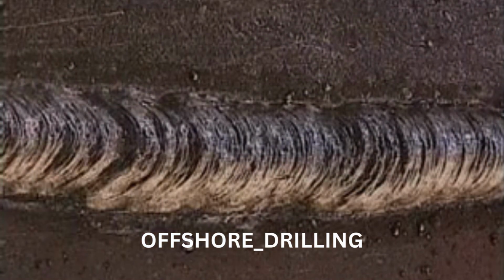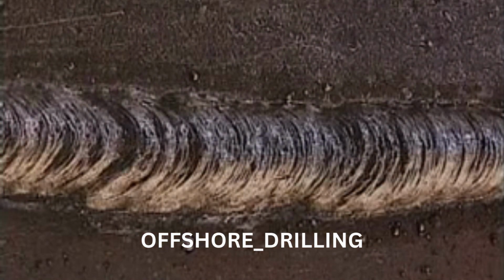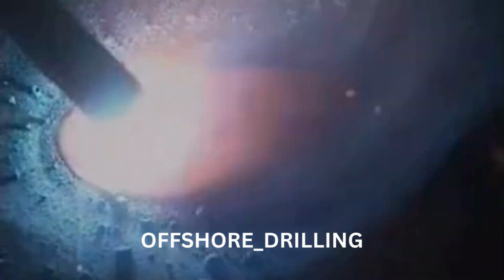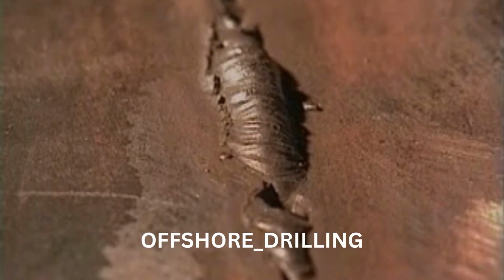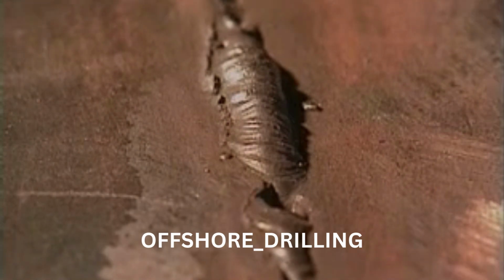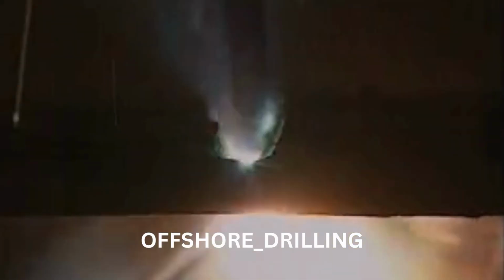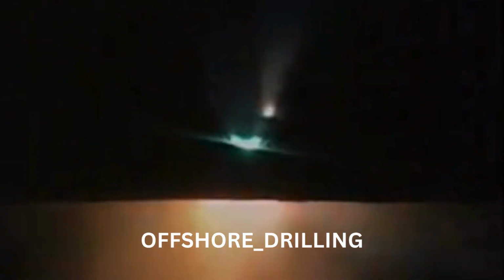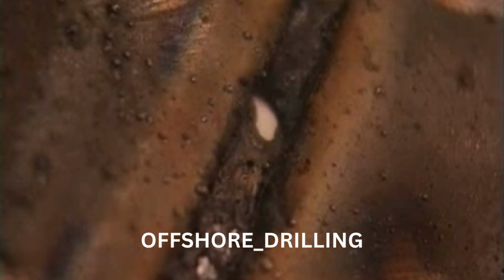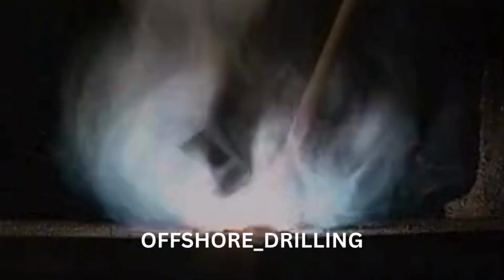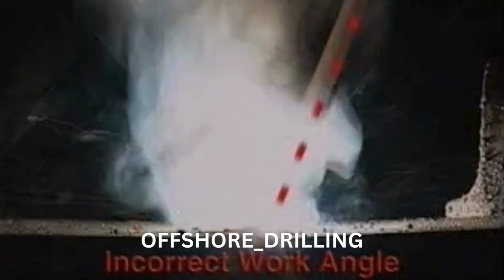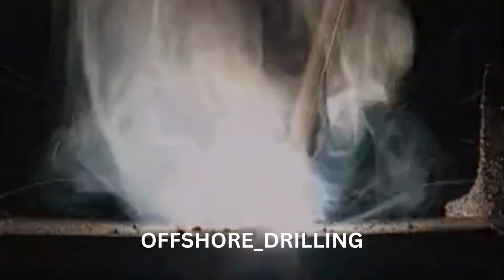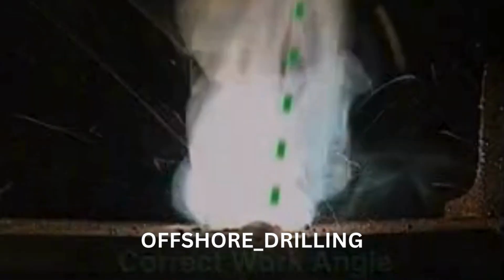A wide and unevenly shaped bead indicates a slow travel rate. This can allow too much filler material to be deposited, resulting in overlap. A notch at the edge of a weld will become a focus point for stress and may eventually fail. At very low speeds, the torch will heat the base metal to the extent that it melts away, resulting in burn-through. A lopsided profile with overlapping on one side and undercutting on the other indicates an incorrect work angle. Aim to keep the work angle perpendicular to the joint to avoid pushing filler over to one side.